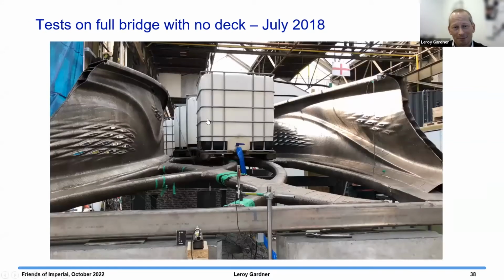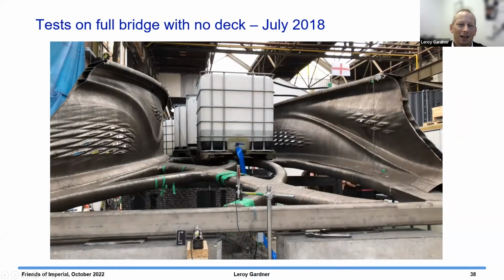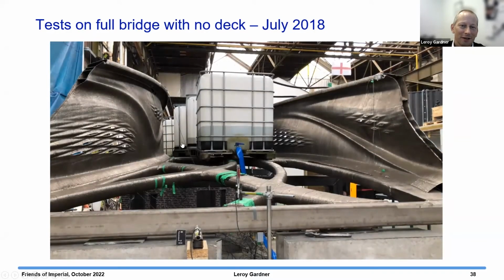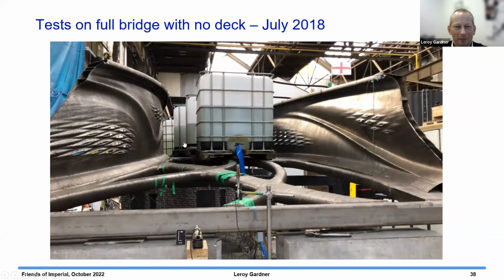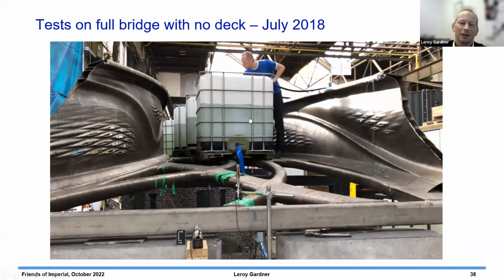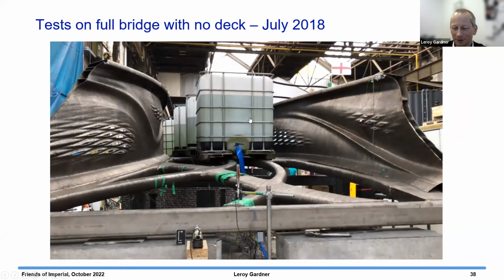And then the other main load case was vertical loading. And in this case, we used water tanks. So the water tanks are 1 meter cube. You fill them up with water, and that's about 1 ton of loading per water tank. And you can see us filling up the tanks. We were trying to keep this relatively uniform, so we got uniform loading along the length of the bridge.